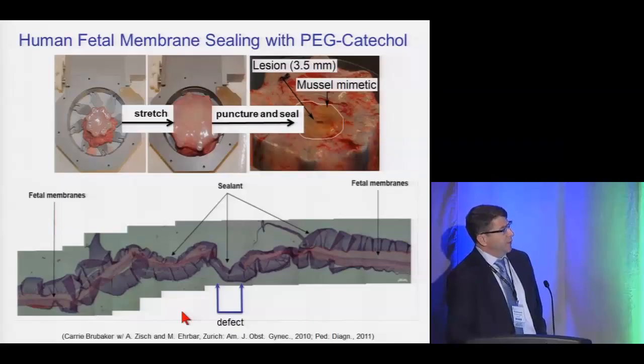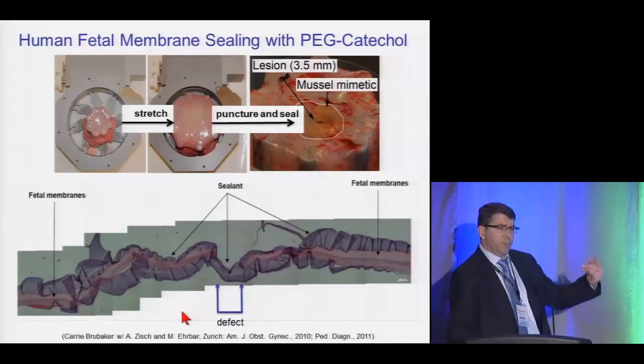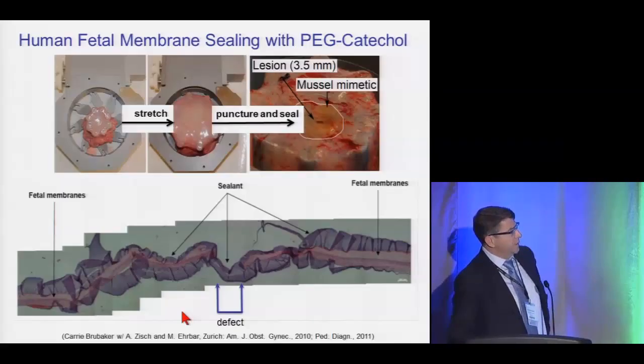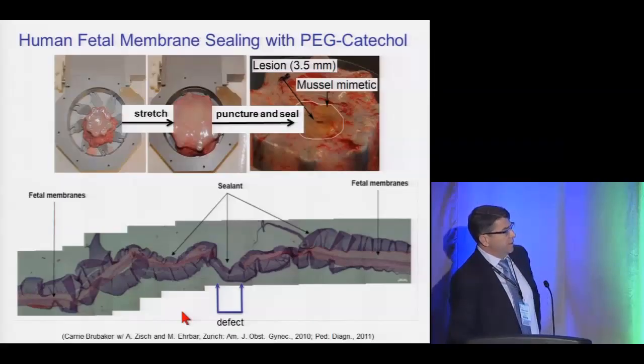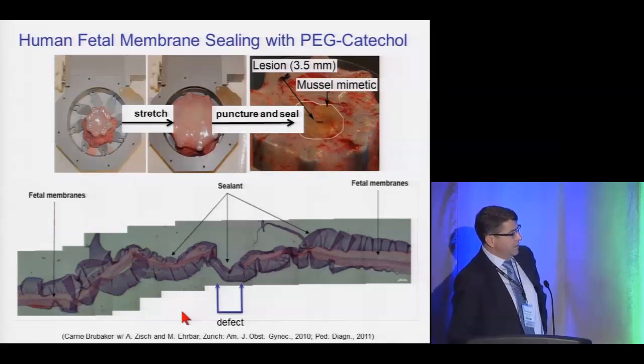And then we simply apply the liquid from that applicator I showed the picture of onto the tissue, let it solidify, and then examine the strength of that bond. If you cut through and do histology through the middle of this defect, you can see the result shown below, which is the fetal membranes here in pink in the middle. The darker material is mussel mimetic adhesive, which shows very good adhesion to the tissue, and importantly also bridges this defect here.